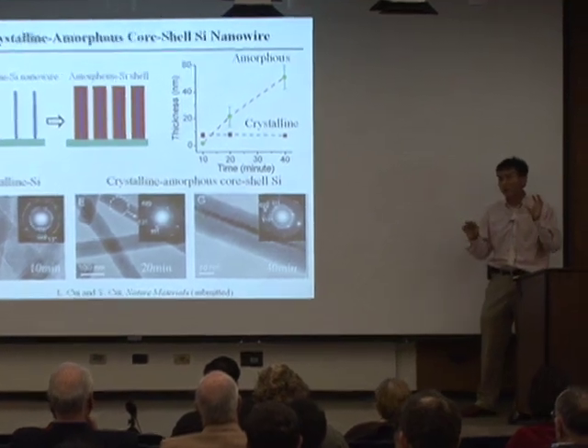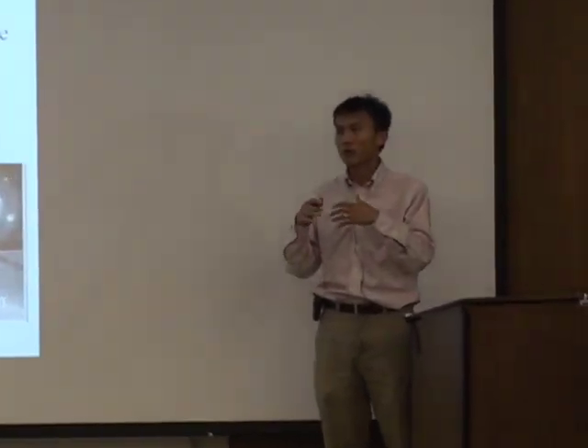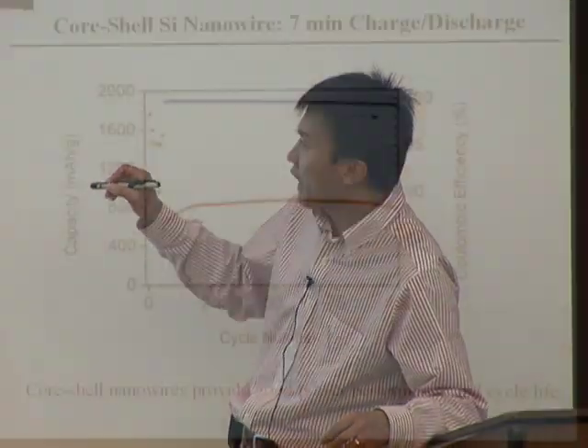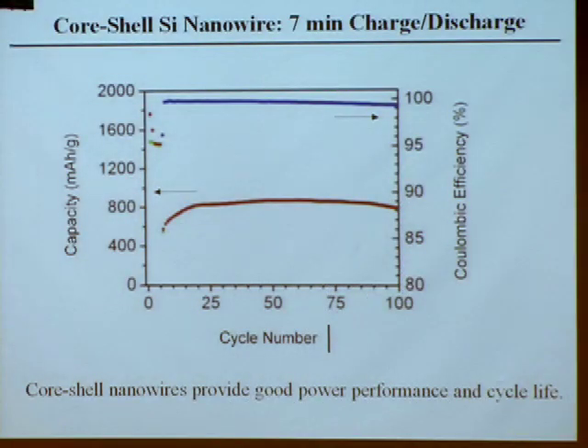So you worry that maybe you waste this weight or volume for the batteries. Indeed, you are not wasting much, only 2%. But the payback you gain is huge. This is the cycling data, capacity versus cycle number. This we run for 100 cycles. We run at an extremely fast rate, only using 7 minutes to charge up your battery and discharge your batteries.